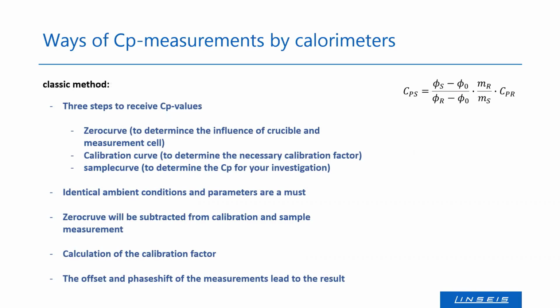So the classic method is, I think, the oldest and the easiest way to measure CP with DSCs. Basically, we need 3 steps here to receive the CP results. At first, we need the zero curve. This is just the crucible in the measurement system without any sample or reference material. This is important to get some information about the measurement system itself. Under the same conditions, we can then measure the calibration. We have to determine the calibration factor for the CP measurement, so we need to heat up a reference and calibration material here. For example, often we use sapphire. And last but not least, of course, important is the sample measurement. Of course, we want to determine the CP for our investigation.